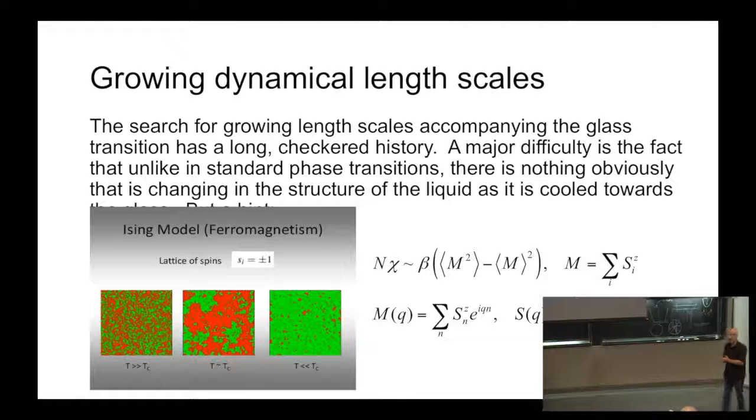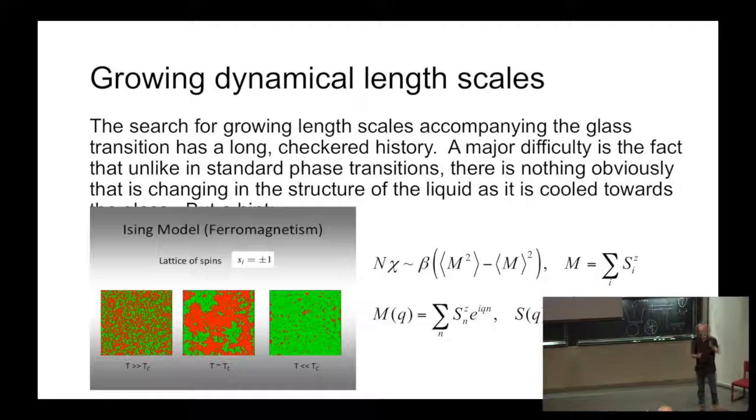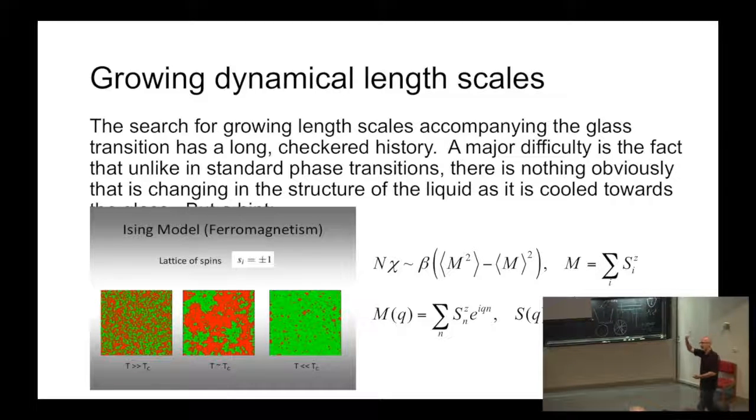But as I said before, if you look at the dynamics, that is, if you look at the snapshot of a system at time t equals 0, so at the initial time, and then time t equals delta tau, the particle positions have moved. That's what that movie showed you, the Weeks and Weitz movie showed you. And if you overlap these two configurations, then you can clearly delineate regions where, let's say, some collective motion has occurred.